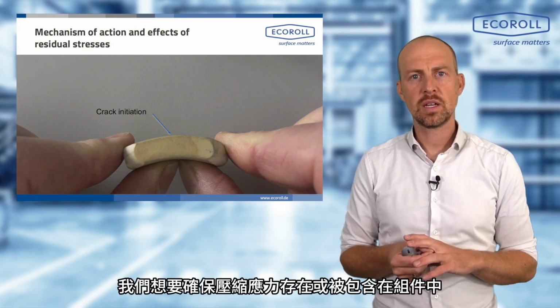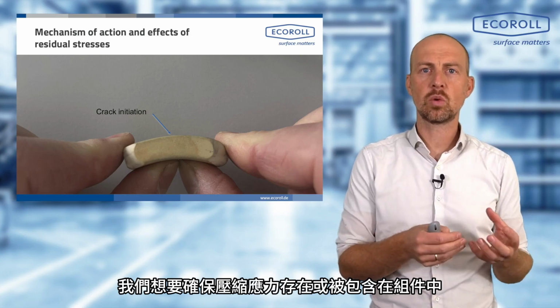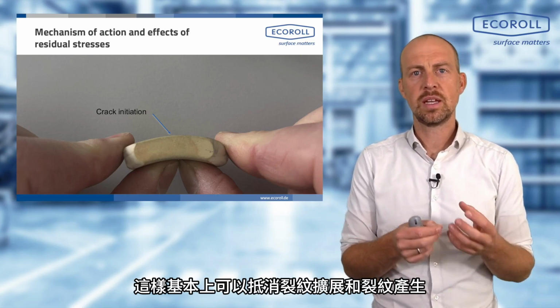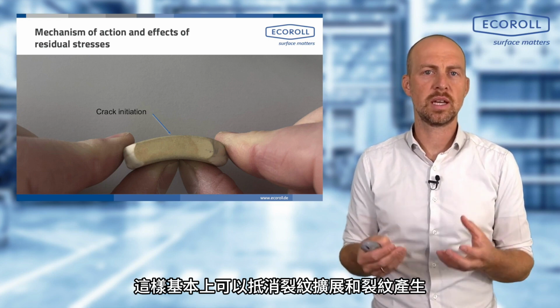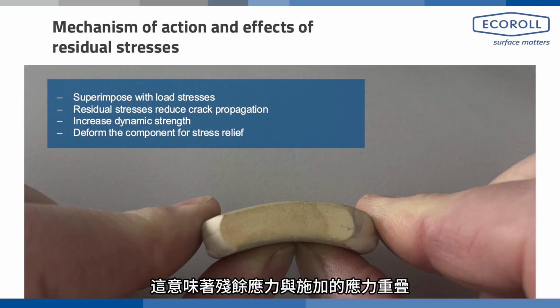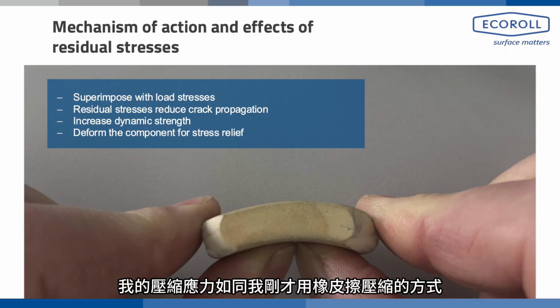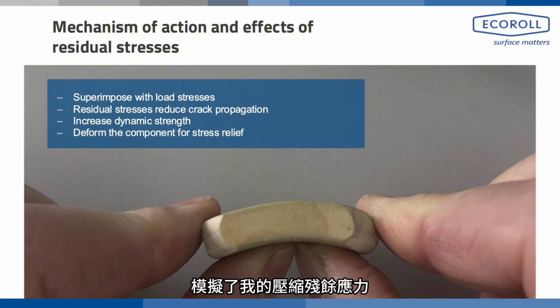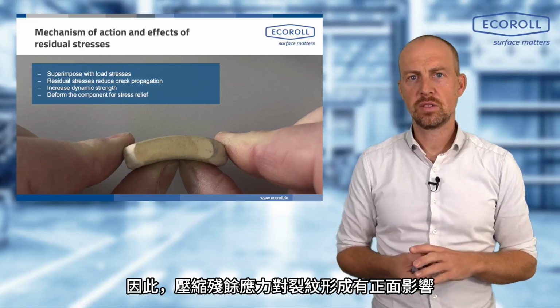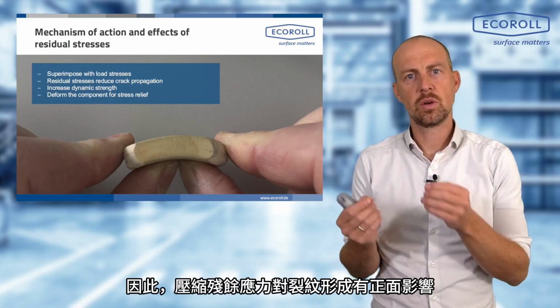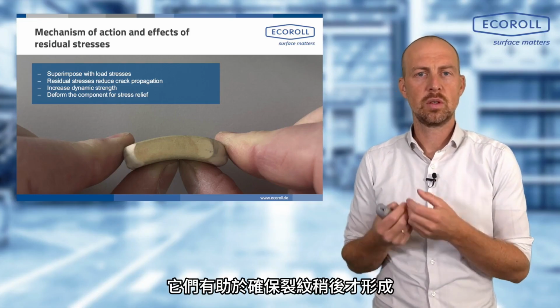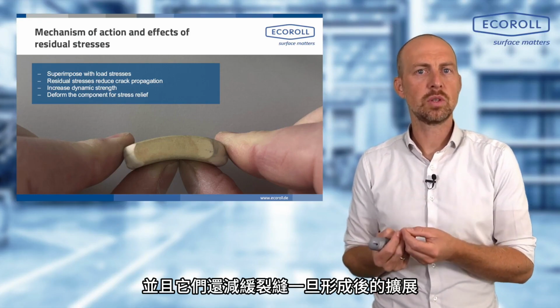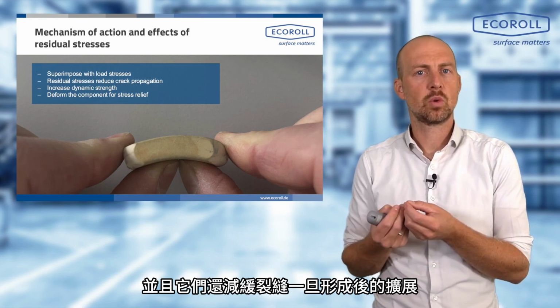We want to ensure that compressive stresses are present in the component, which then essentially counteract crack propagation and crack initiation. That means residual stresses overlap with the applied stresses. My compressive stress, what I just did with the eraser by compressing it, simulates my compressive residual stress, and these overlap with the load stress from the bending. So compressive residual stresses have a positive effect on crack formation. They help ensure that cracks form later, and they also slow down the propagation of cracks once they have formed.